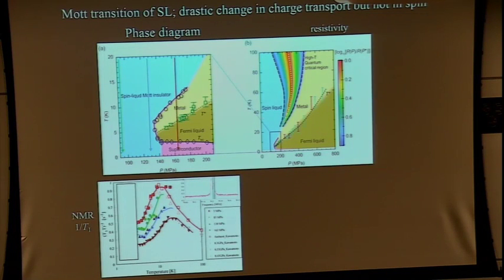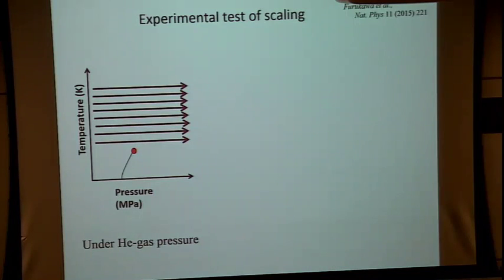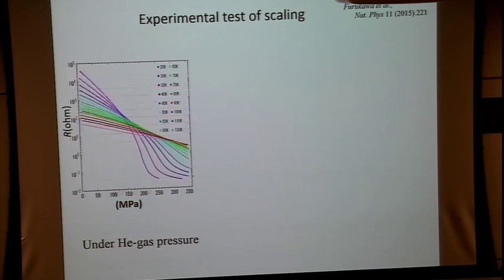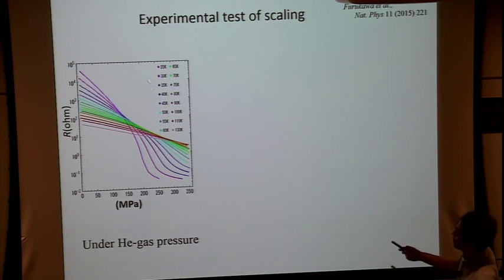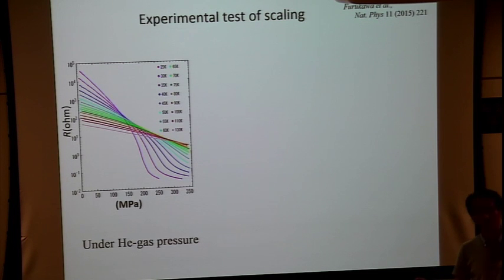Okay. So what we did is that the resistivity behaviors in these regions as functions of temperature and pressure are scaled in a quantum critical manner. What we did is very simple. Temperature is fixed, for example here, and then pressure is swept, and resistivity is measured. This measurement is repeated at different fixed temperatures. The obtained results are like this. For example, at 25 kelvins, the resistivity is insulating and gradually changes. This is the high temperature data, so there is no first order transition. It's a crossover region, so the change from the insulating state to the metallic Fermi liquid state is smooth. It's very continuous.